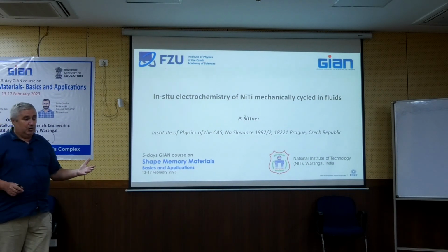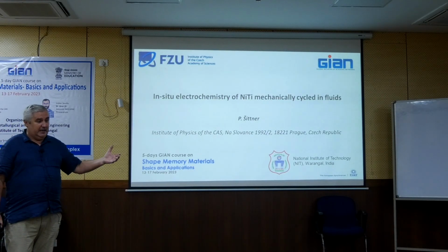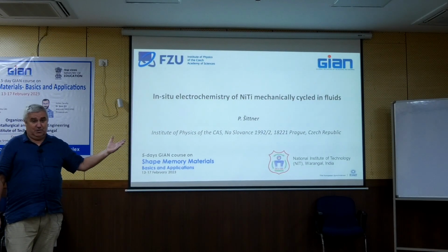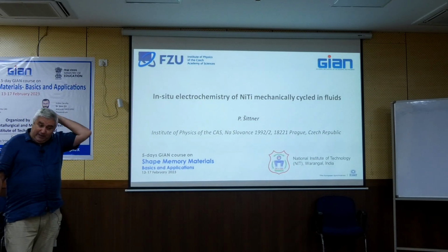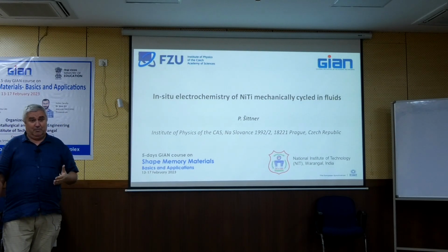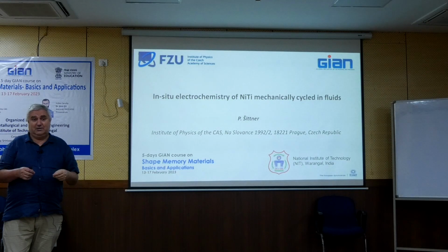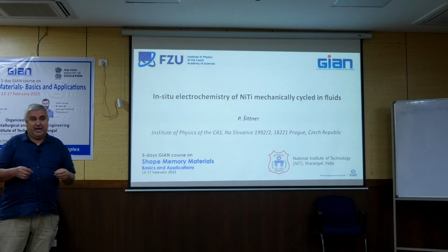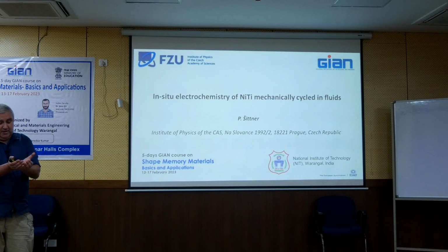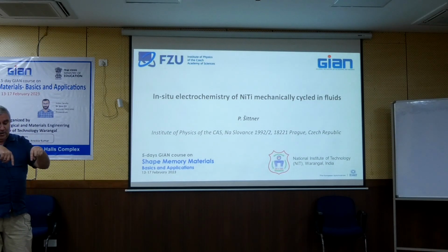And this is important for corrosion because the metal, when it's exposed to corrosion, it degrades and you have problems. Corrosion takes place over years, but you want to study it in the laboratory, so you accelerate it with an electrochemical system. So you have some electrochemical cell. You have the material inside, you have the electrodes, put the electric current, you accelerate the corrosion, and you determine it statically. And the nitinol, as I said before, is protected by very thin oxide.